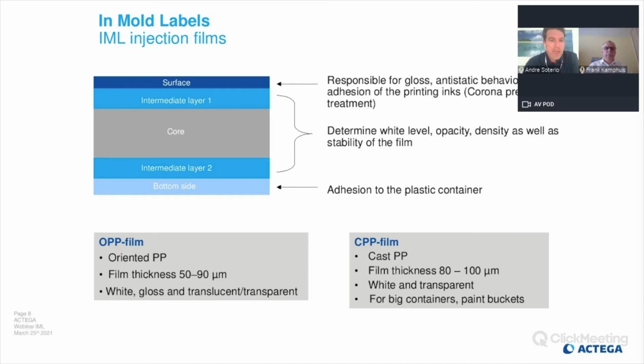Here we have another important point when using IML, which is of course the combination of the film, inks, and coatings for the printer. One of the main important points is the film usage. In injection molding, most films used are OPP or CPP films. Oriented polypropylene can go from 50 to 90 microns. And CPP, which is cast polypropylene, can go from 80 to 100 microns. Cast PP is mainly used for large containers like paint buckets. Both of them can be widely printed by offset or flexo, depending on the printing method decided, or even digital.